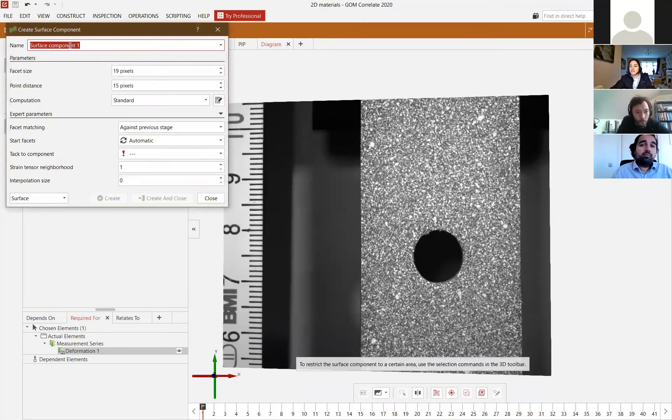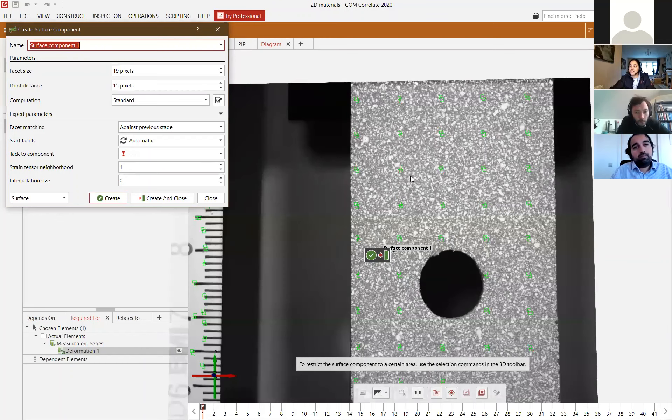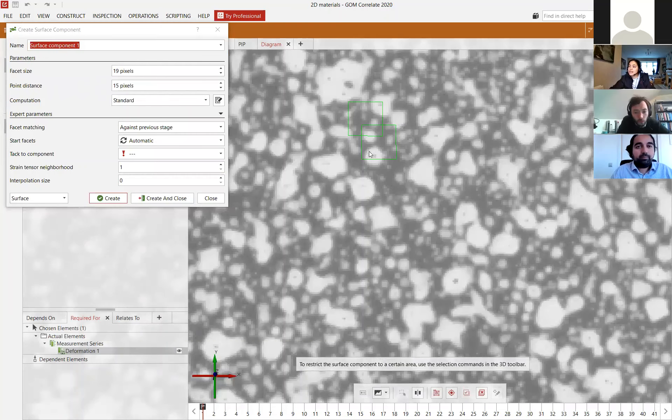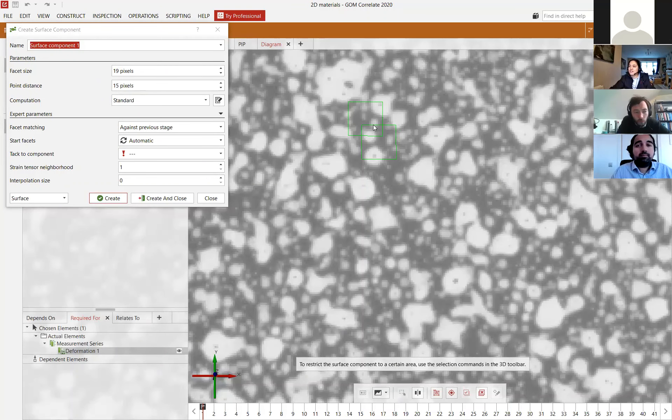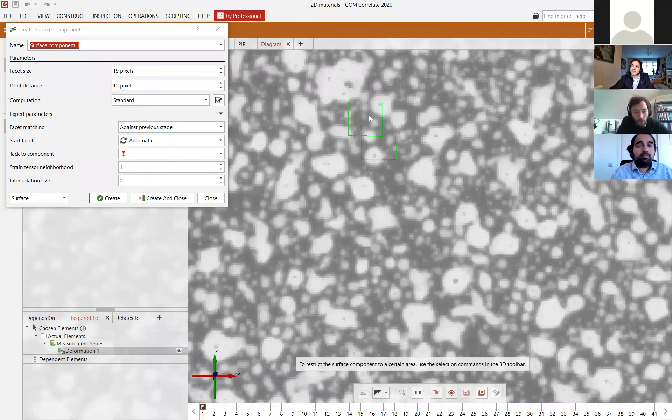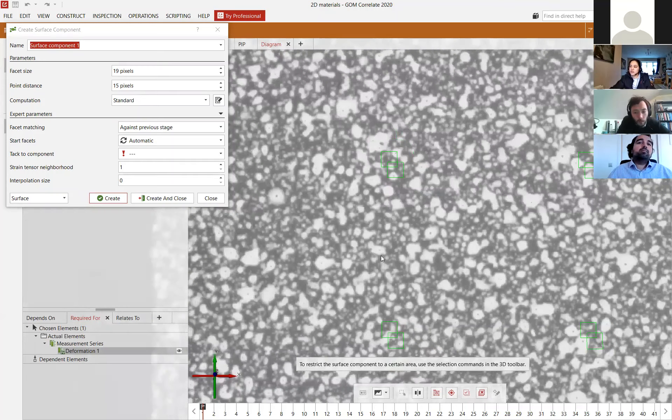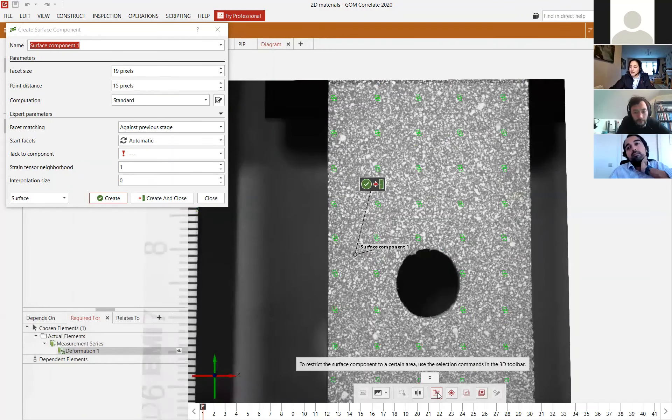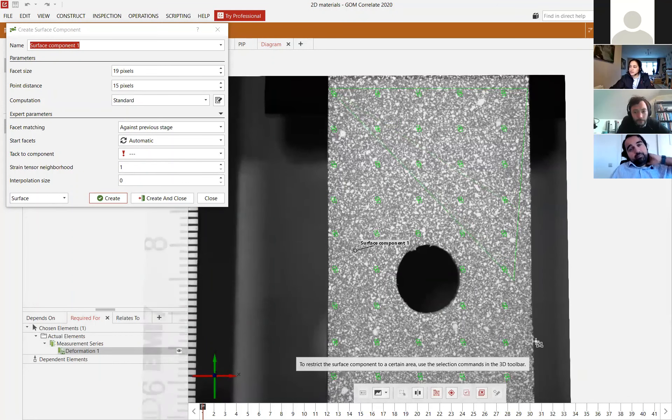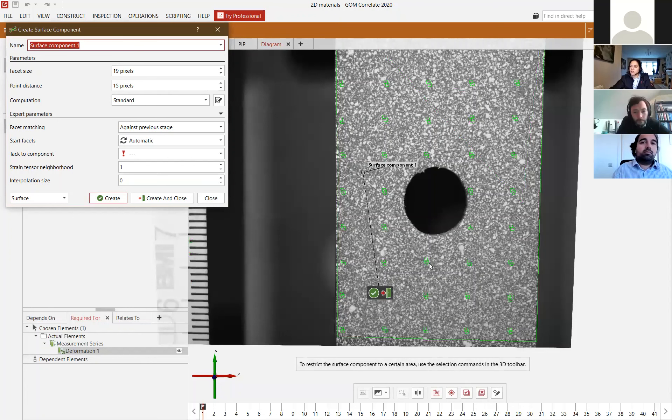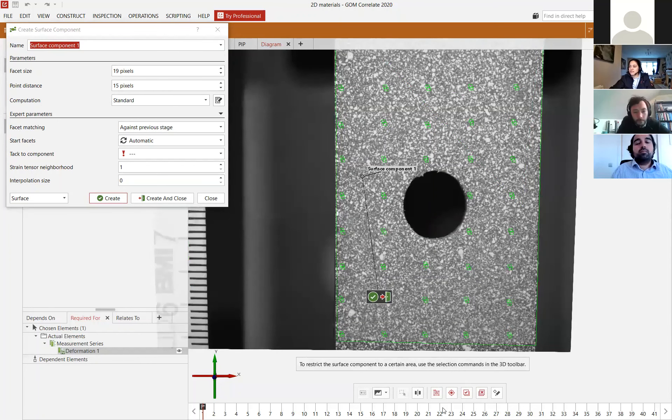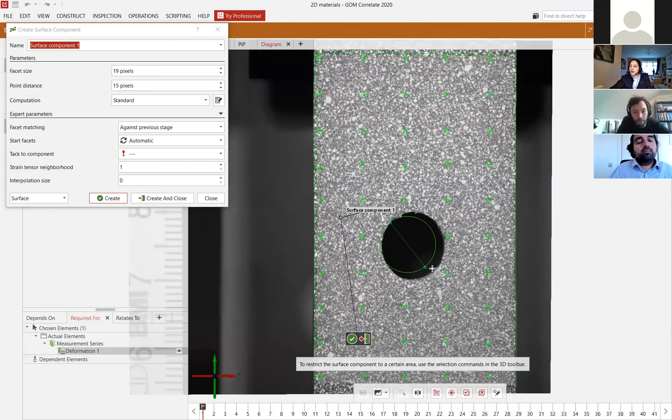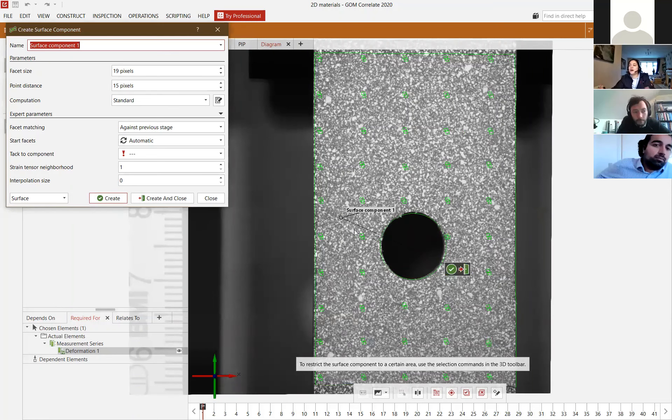The next step is to define the components. So we're going to ask the software to have a look and define some facets. So the facets are these green squares. And each of these facets will have its own fingerprint because of the stochastic pattern or the random pattern that's been applied with spray paint. Each box here will have its own pattern. And this is what's going to then be matched image to image. This is what the software is going to be using to do the correlation. Within our software, we always recommend that you draw a boundary around the part that you're interested in measuring. This way, the software can just focus on the area that you want to measure and not try and measure the ruler, especially with 2D measurements. The software can see quite a lot of areas that perhaps you're not intending to measure. But of course, you just want to focus on your sample.